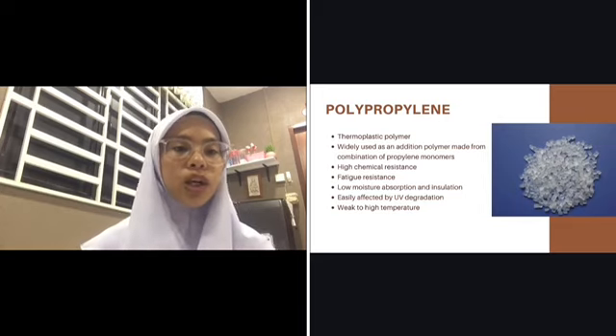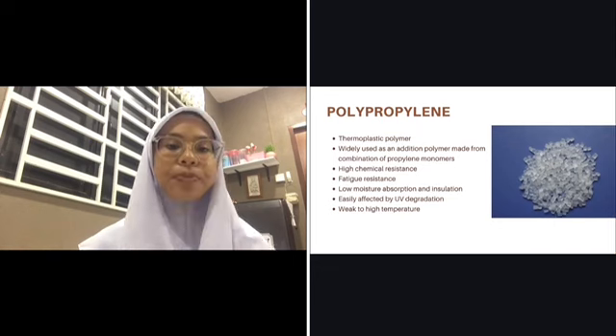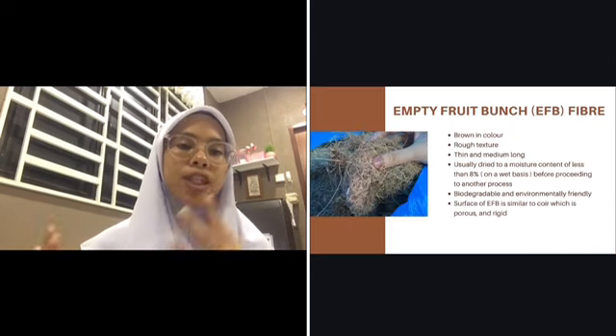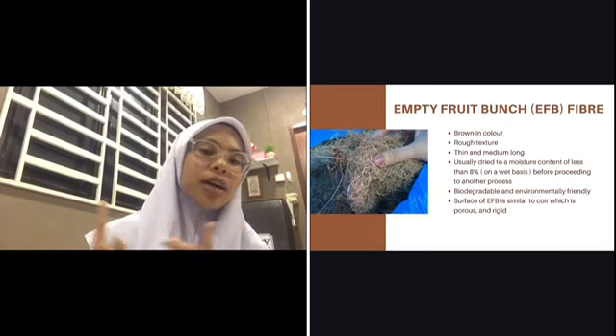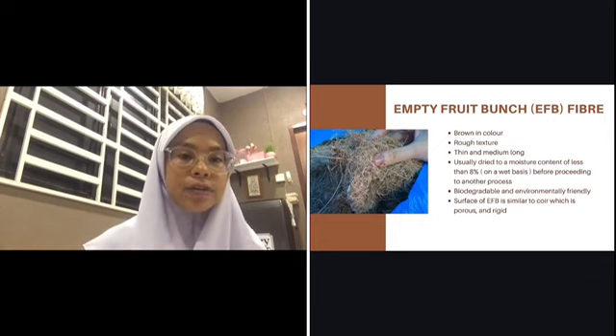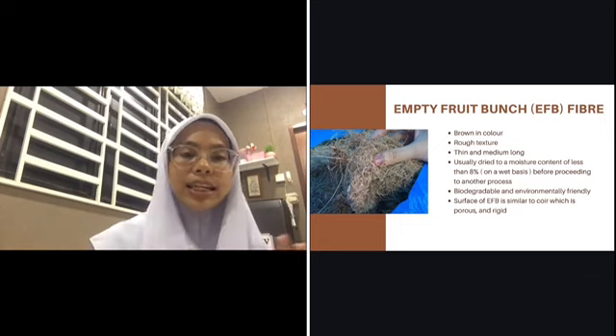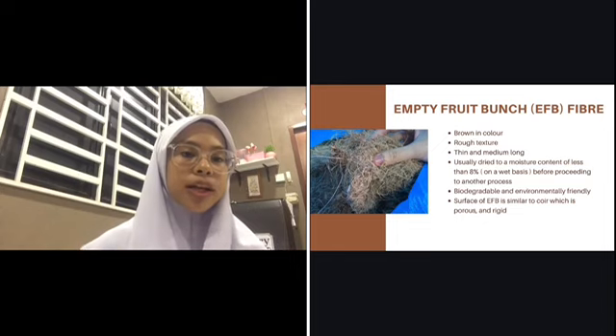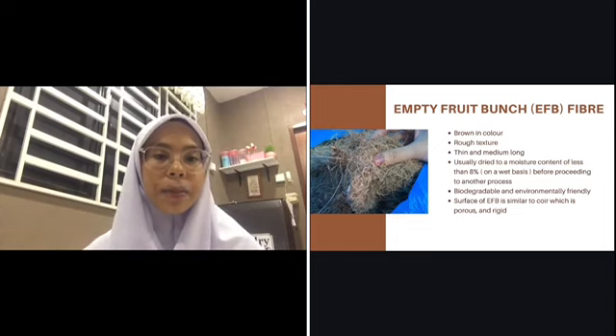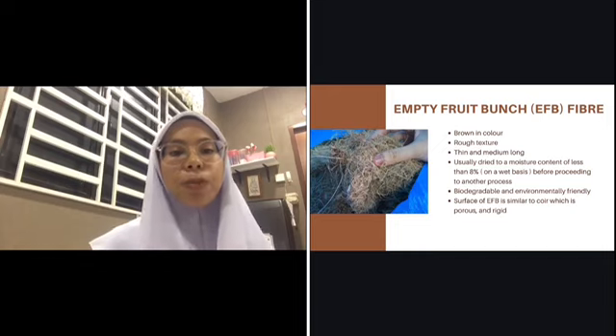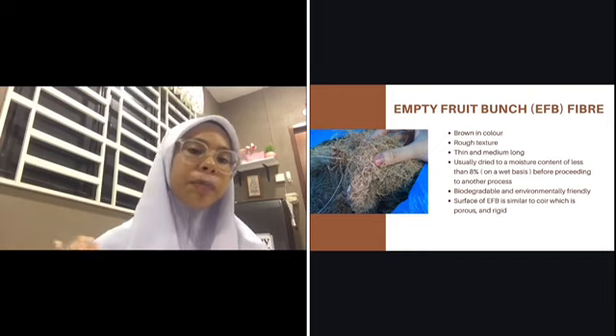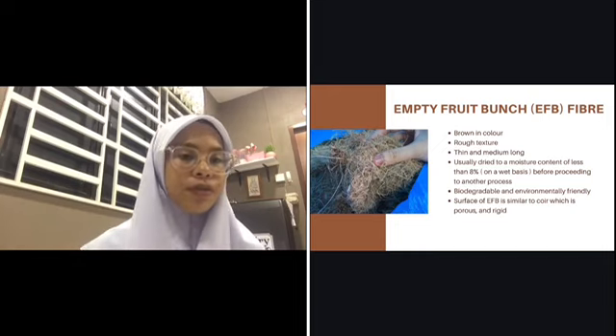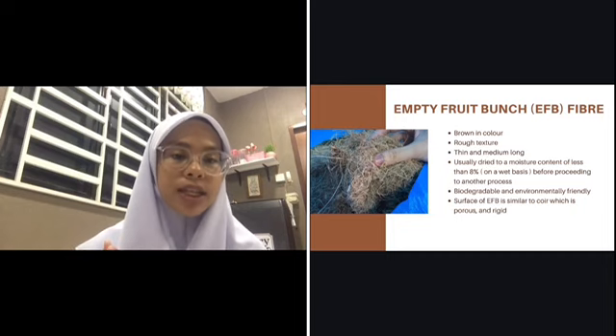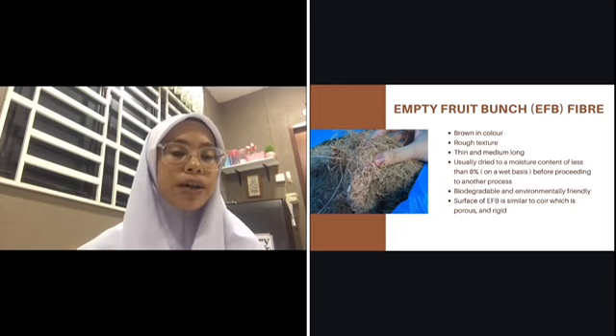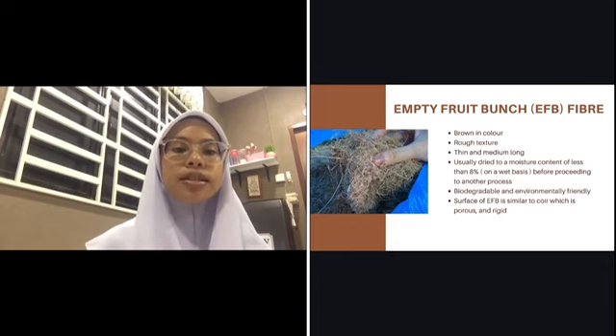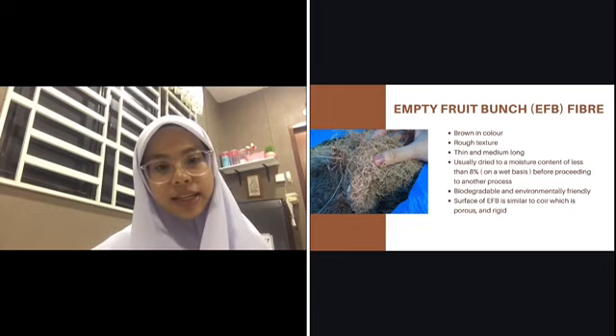Subsequently, I will explain to you about empty fruit bunch fiber. Empty fruit bunch fiber is brown in color, rough in texture, and a medium long and thin fiber, as you can see in the picture. It is usually dried to a moisture content of less than 8% on a wet basis before proceeding to another process, besides being biodegradable and environmentally friendly. The surface of EFB is also similar to coir, which is porous and rigid. Its porous structure results in better interlocking with matrix resin.